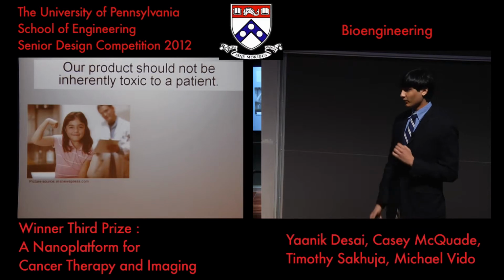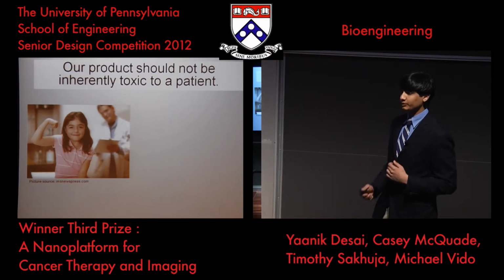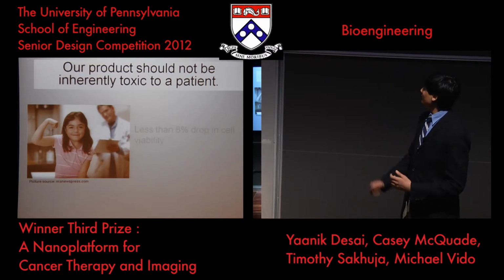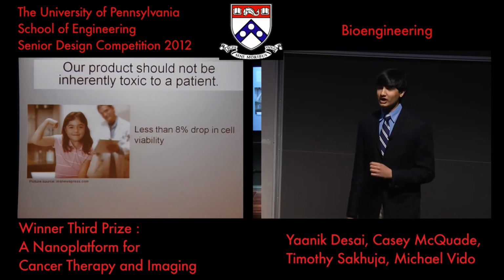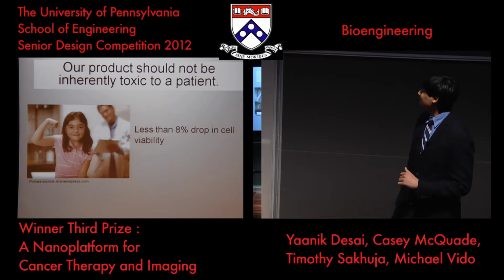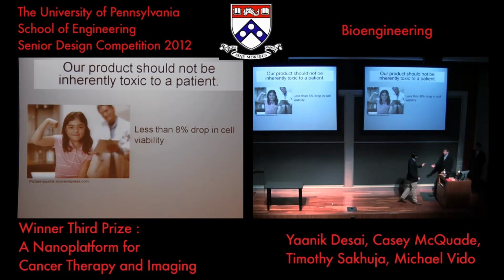But the next thing that we wanted to test, before we propose delivering our micelles into a patient, is to make sure that they're not inherently toxic. We measured this via a cell viability assay, and we saw a less than 8% drop in viability. So we could confidently say that our product is not inherently toxic. So now Mike is going to talk about our crucial final product design.